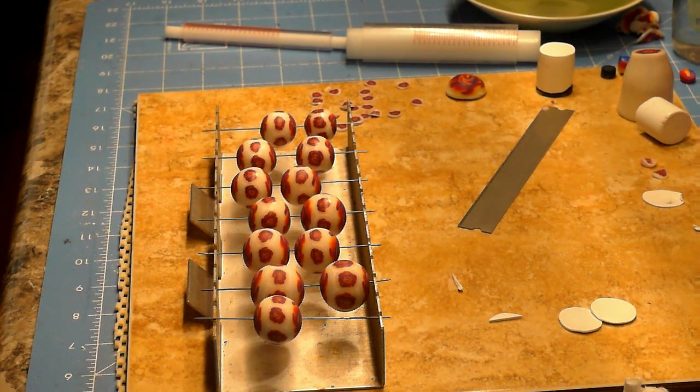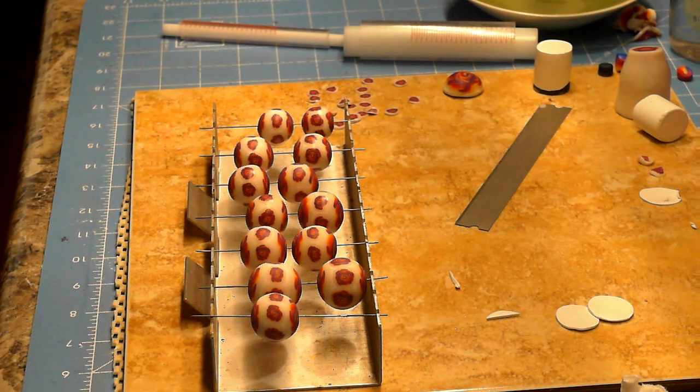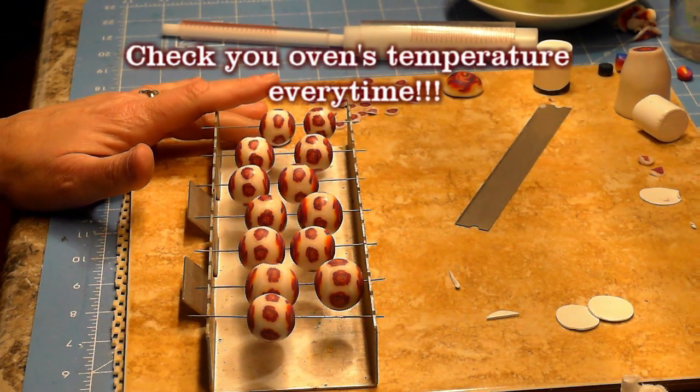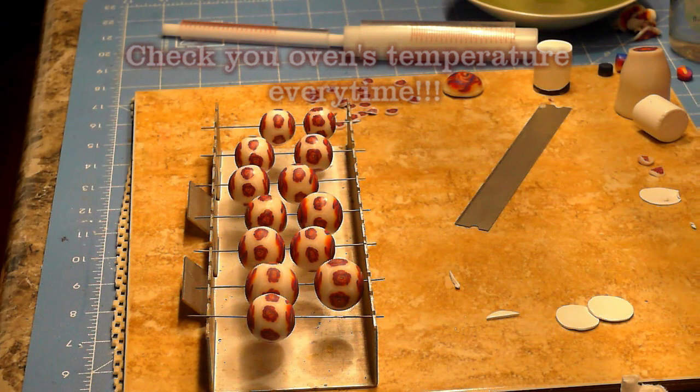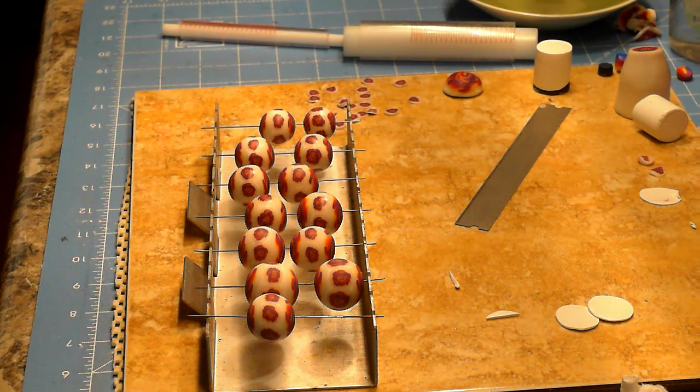So my toaster oven has been heating up now for about 10 minutes. Kato was supposed to be baked at 300 degrees. My oven temperature was set at 225 degrees, even less than that. And it was spiking at 325, almost 100 degrees difference. And so I redid all my beads, and I'm waiting for the temperature to come back down. I lowered it even more. And so it's set now to just slightly below 225 degrees. And I'm waiting for the temperature to come down.